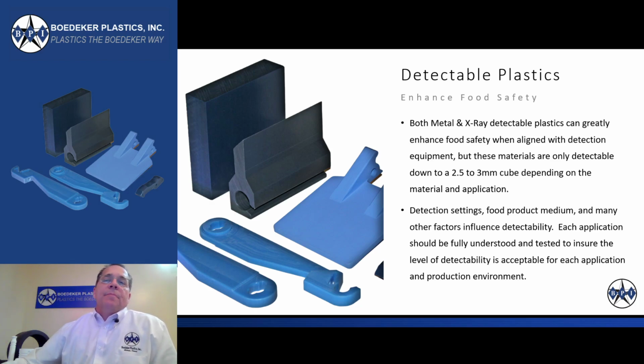In summary, both metal and X-ray detectable plastics can greatly enhance food safety when aligned with detection equipment. But these materials are only detectable down to about 2.5 to 3 millimeter cube size, depending on the material and depending on the application. And as we mentioned, of course, detection settings, food product medium, and many other factors can influence this level of detectability. So each application needs to be fully understood, fully tested to ensure the level of detectability is acceptable for each individual application and product environment.